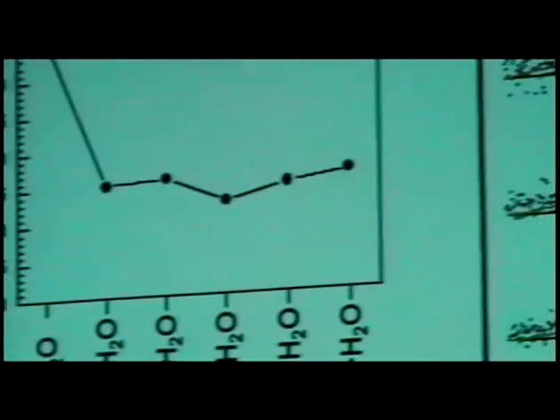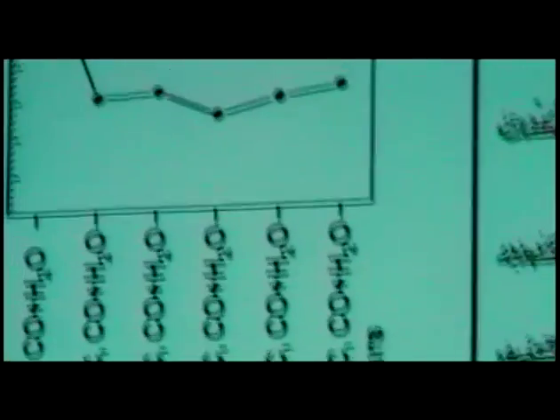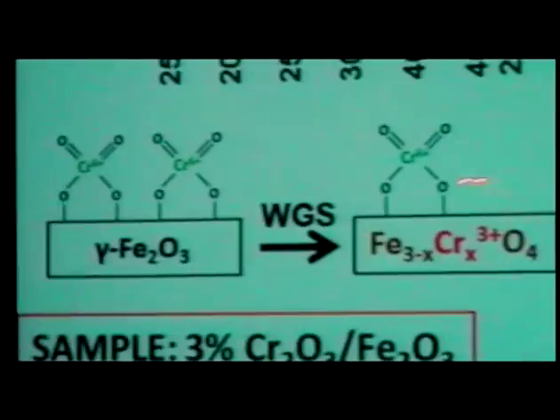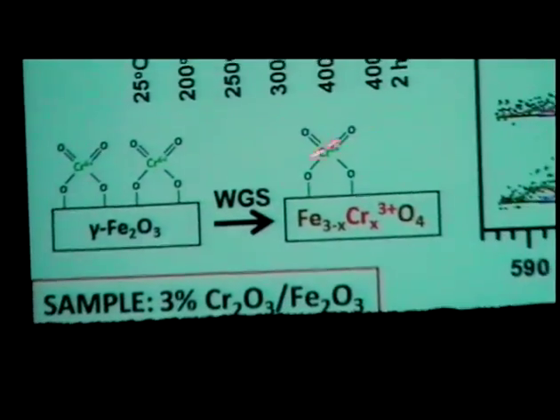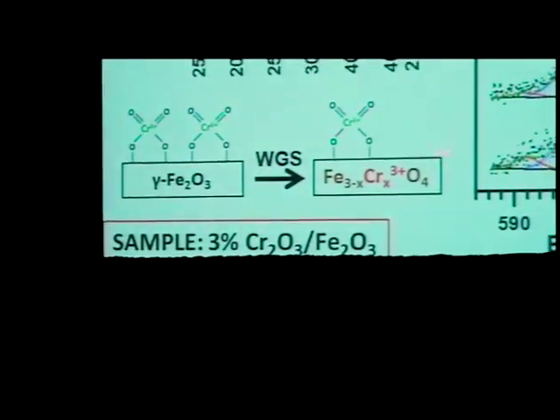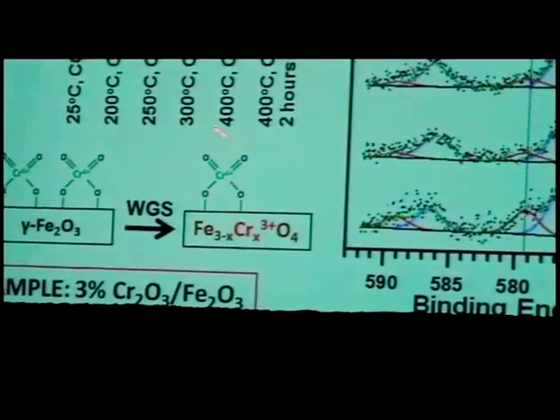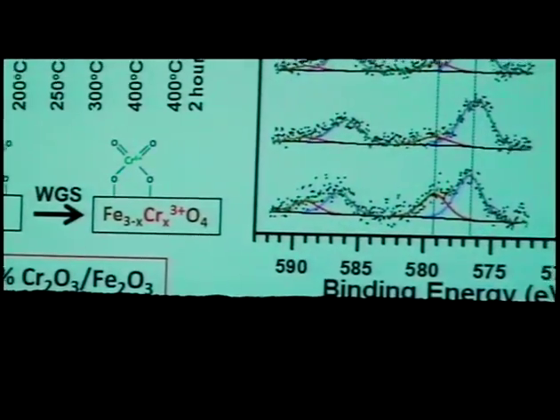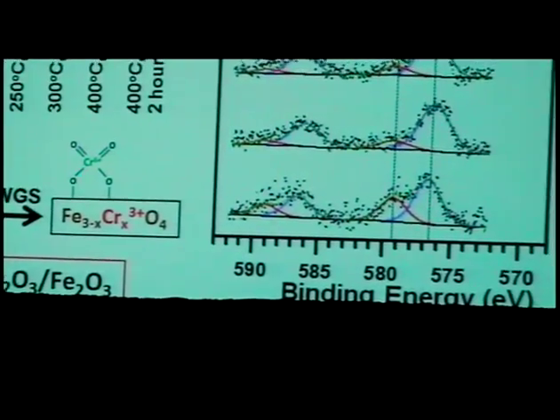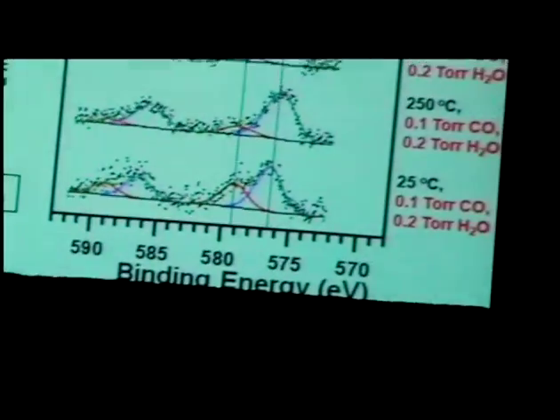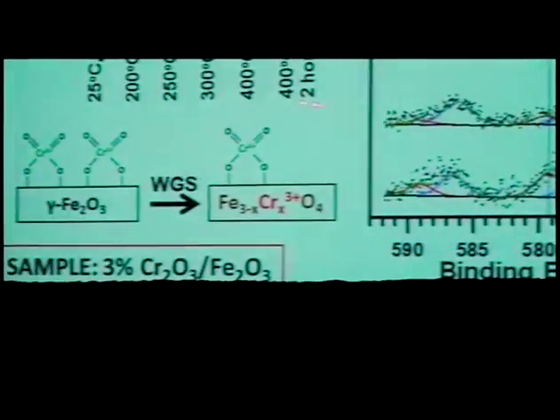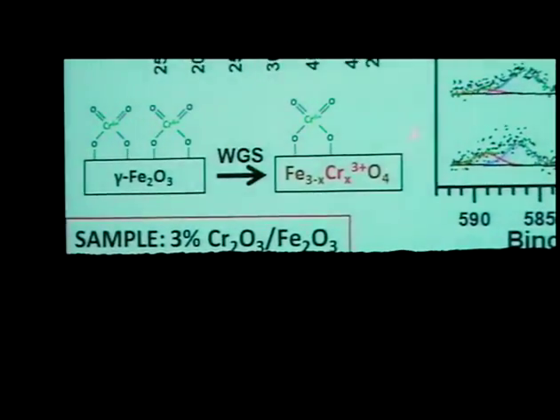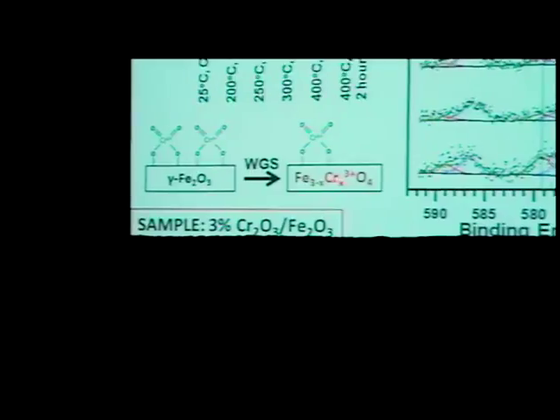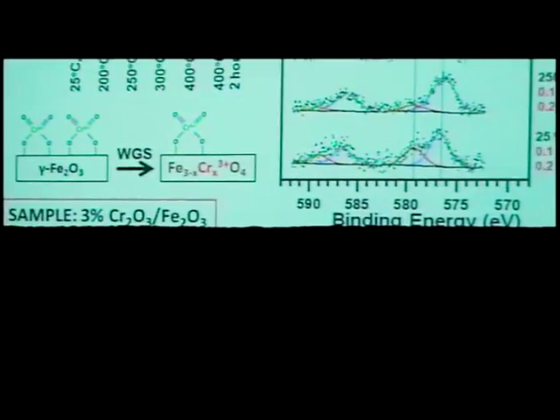You can see here about 15% still retained as chromium 6. And so this raises a question: if chromium 6 is on the surface, is it the catalytic active site, or is it the iron oxide? We know iron oxide can do water gas shift, but if you put the chromium on the surface, is it also acting as an active site? I should point out that we measured the BET surface areas, and indeed, the chromium is a stabilizer, and it increases the surface area of the iron oxide. But the question still remains, is this an active site?